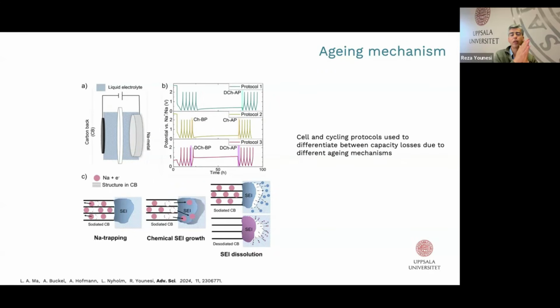If there is any possible reaction between electrode and electrolyte, that could happen simultaneously in the cell. After that, we discharge the cell again to see if we can form more SEI. If we can, that indicates part of this SEI was dissolved during this pause or relaxation time, and that's why we can consume more current or charge to form SEI again.